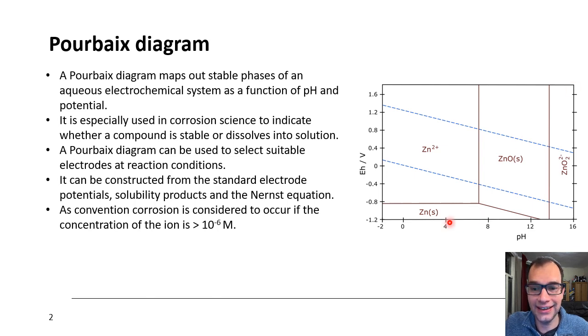What you see on the x-axis is the pH, and on the y-axis is the potential versus the standard hydrogen electrode. So the potential the material is experiencing. So basically what you can see is, for example, for pH 4 and a potential of 0 volt, you can see that zinc is most stable in its 2+ state. Well, when we then reduce the potential, for example, to minus one, then metallic zinc is most stable.